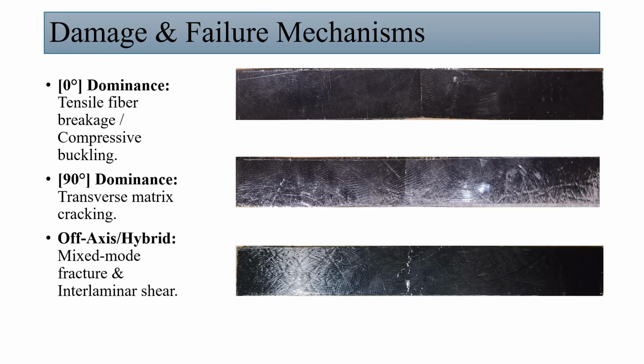Beyond the numbers, the physical failure modes were distinct. The 0-degree laminates failed through sudden tensile fiber breakage or compressive buckling. The 90-degree layups failed exclusively through transverse matrix cracking, essentially snapping the resin. However, the off-axis and hybrid layups experienced much more complex degradation, including interlaminar shear, delamination, and mixed mode fractures. Capturing these complex progressive failure modes numerically is exactly what makes composite simulation so challenging.